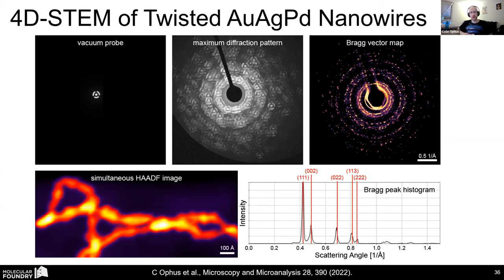So we have a paper on this in Ultramicroscopy where Steve Zeltman is the first author. The patterned apertures are in particular what we use for thick multiple scattering materials. Once you're above 20 nanometers, or above 50 nanometers for lighter elements, and sometimes we go as high as even 300 nanometers, as you saw for our samples, you get a lot of contrast in your diffracted disks. And so if you stamp this pattern into it, you have these hard edges that we can use to detect the position of these disks.